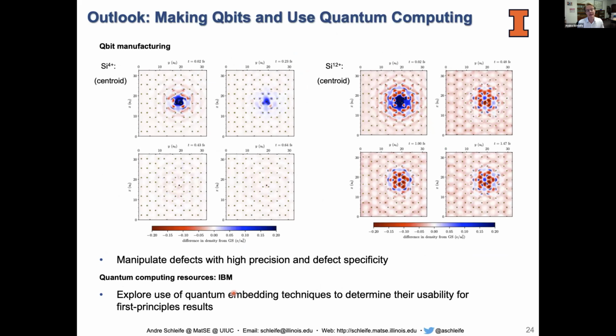But in the paper that you can find in the literature, for instance, Giulia Galli's work, what they're essentially doing is they're focusing on a defect in a semiconductor, let's say. The semiconductor can be described by DFT on a classical computer, and then that provides input for the quantum Hamiltonian of the defect states, and you can then obtain insight into the defect states. That smaller problem parameterized by DFT is where the embedding comes from. It's sort of like this defect is embedded in a bigger piece of material, let's say. That is what then is run on the actual quantum computer. But again, I just want to be clear, we have not done these simulations.